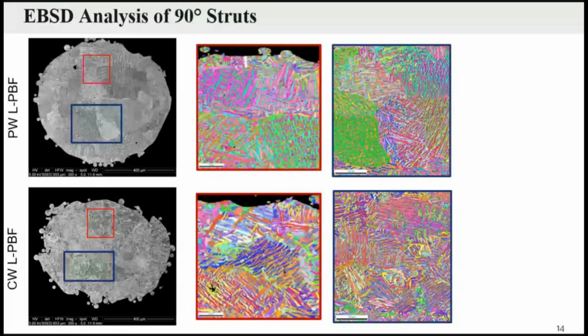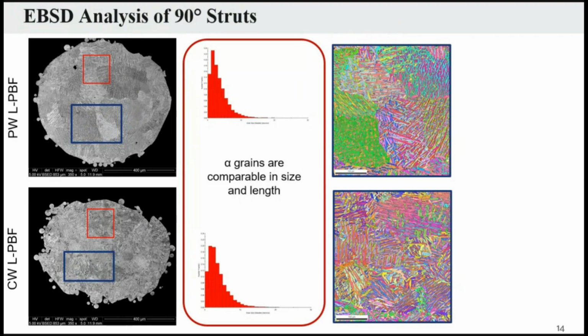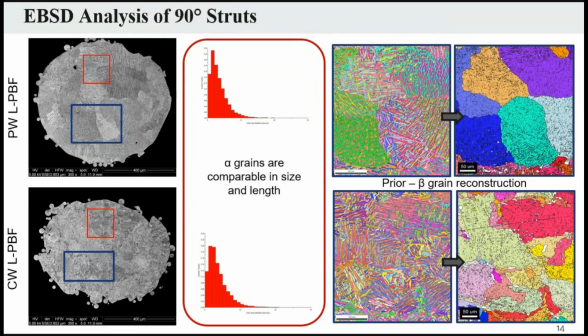As you can already see, there are clear differences that are evincible from these SEM images. And in particular, these differences are not related to the alpha grains, which are comparable in size and length, but are mainly related to the prior beta grain reconstruction. And in particular, you can see that for the pulsed wave, there are way larger grains with respect to the continuous wave laser powder bed fusion. But how does this impact on fatigue?